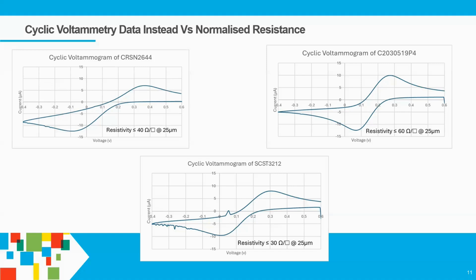I've got a couple of examples here of 3 different inks. I do apologize for this one, it does have a sort of spike in it. This is from a printing process, not the material. And you can see here you've got the oxidative peak. I'm not going to go into details about going from baseline and so on, it's just to give you representations. You have one which is quite low at 40, one at 60, and one at 30. And you can see the one at 60 actually gives a much higher oxidation peak, even from baseline, compared to the other two. And this one is 30 ohms per square at 25 microns. So it's not really any relationship.